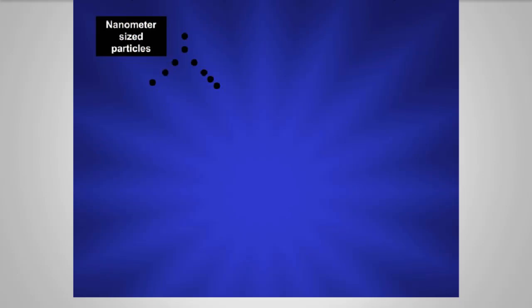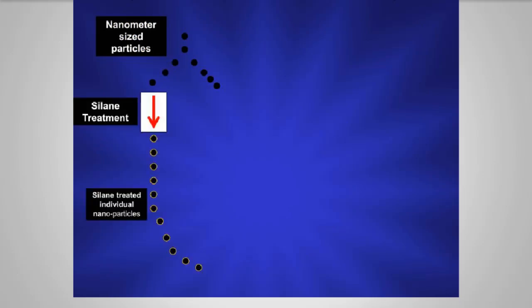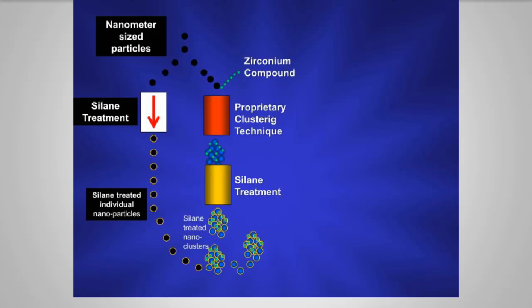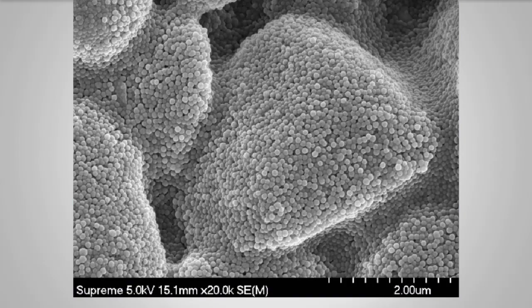Some are coated with silane coupling agents, others are mixed with zirconia and formed into clusters through an agglomeration process. These particles are then mixed with various resins, and here we have an SEM of the finished composite material, consisting of nanoparticles that provide high polishability, and these large clusters of nanoparticles that help provide overall assembly strength. This is actually a very nice material, and is probably the go-to composite that I'm using most often in my practice today.